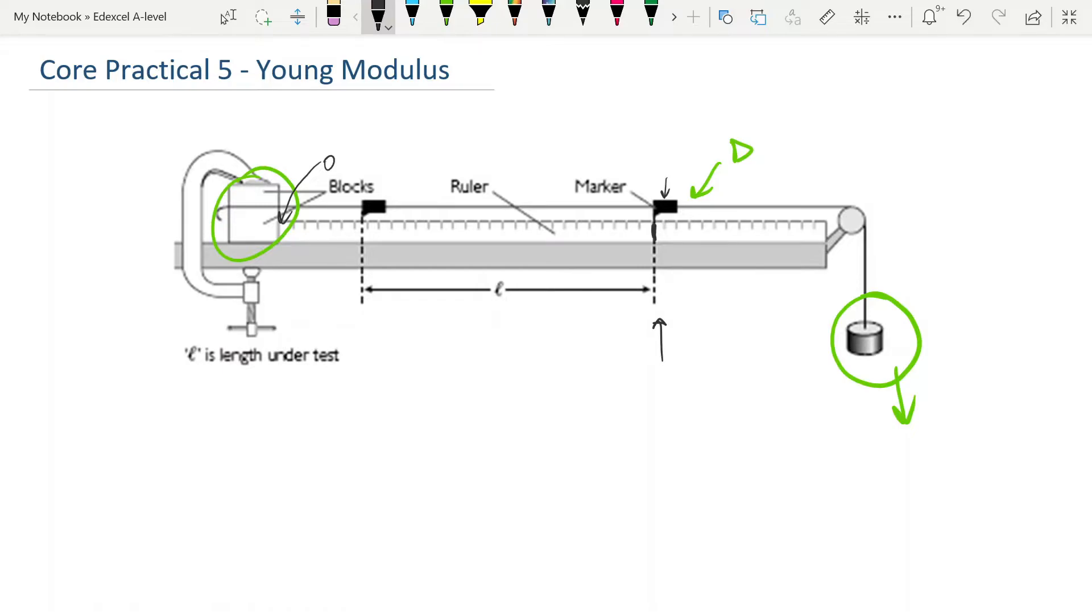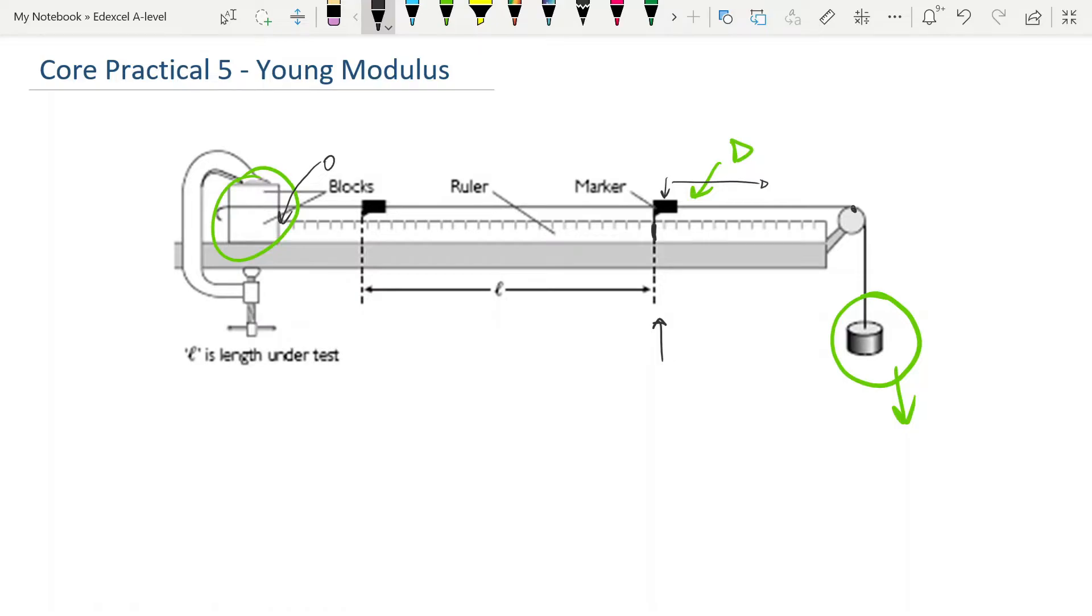Without any tension in the wire, so you can just hold it over your pulley here and measure the length to your marker. Now do try to have your marker as far along this as possible, considering that you're probably going to get a maximum of maybe 15 millimeters extension. So you have it as far along as possible allowing for 15 or maybe 20 millimeters from the end, so that the wire can extend. And then all you do is add masses on here.